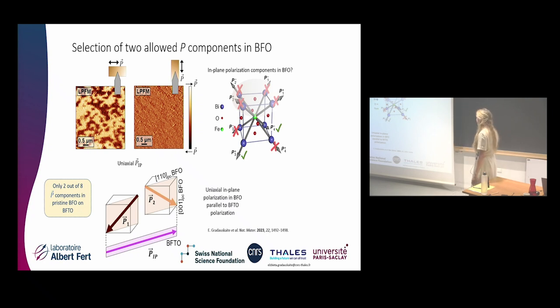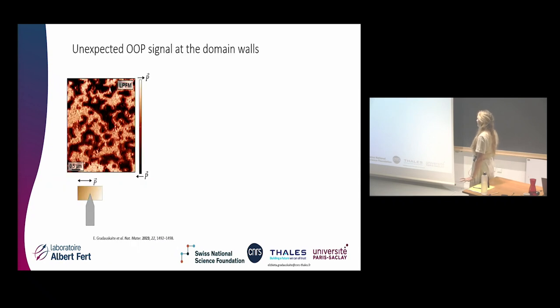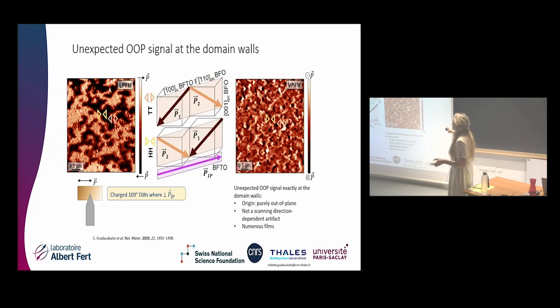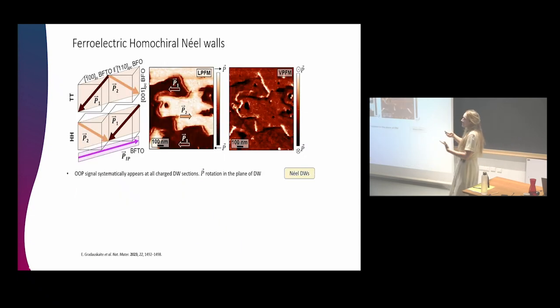What was very surprising, in fact, is that we have these 2 domain variants in plane in BFO, and we noticed that at every domain wall, especially whenever it was a head-to-head and tail-to-tail charged domain wall, we started seeing some unusual signal in vertical PFM, which looked a bit like spaghetti. It was a bit strange at first. We did a lot of tests to really confirm it's not some spurious artifact. And indeed, there's some out-of-plane component coming up exactly at the wall. And that, of course, implies some type of ferroelectric polarization rotation in the plane of the domain wall.